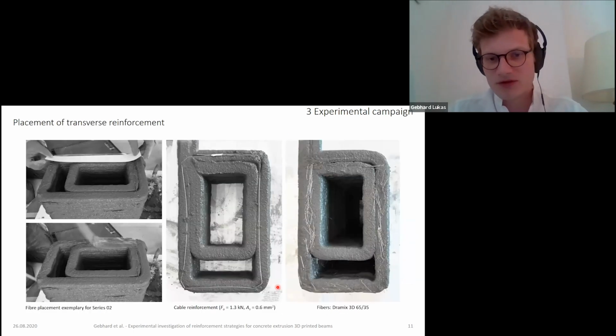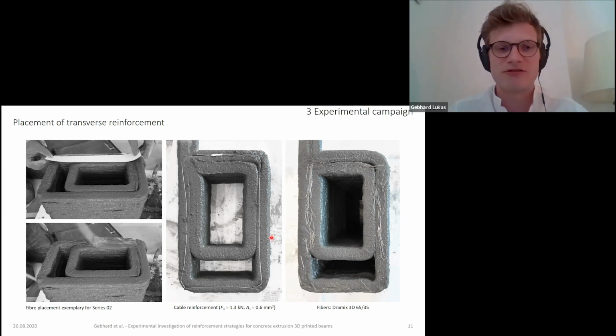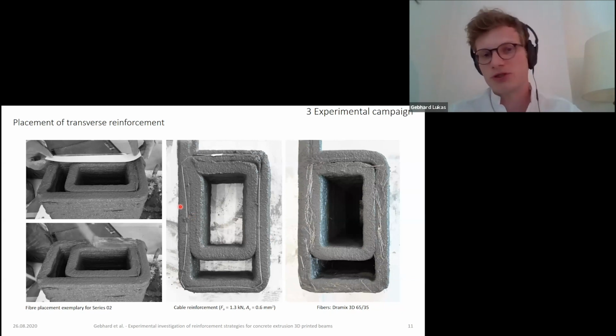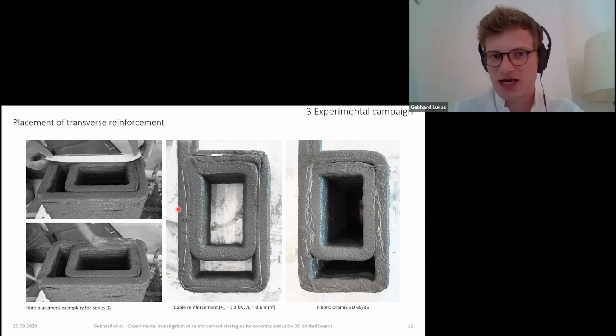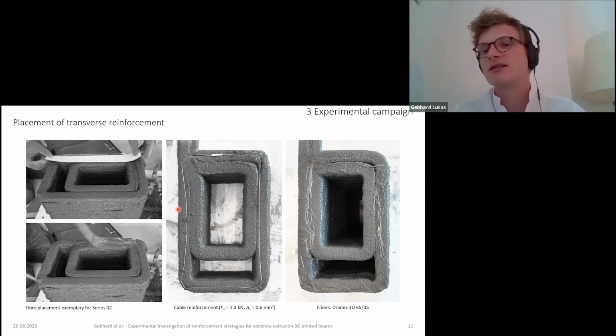Now, for the transversal reinforcement, here some impressions from the placement of the fibers. So all the reinforcement was placed manually to have a good control over the amount of fibers and cables placed. And the fibers were prepared before the printing on these magnetic strips with a plastic foil to have a faster placement of the fibers during printing. The cable was pre-bent to fit the shape of the concrete cross-section, and the fibers were then placed. As a cable, we also used a high-strength cable with an ultimate tensile load of 1.3 kilonewtons, and as fibers, we used conventional hooked-end fibers type Dramix 3D 6535.